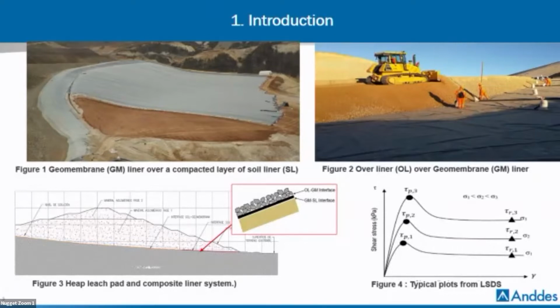You can see in this picture, following the ASTM, the typical behavior of shear strength versus displacement. The shear stress generally increases until the peak shear stress. It should be noted that beyond the maximum displacement of the test, there is no additional reduction of the shear strength, indicating that in this specific case, as in many others observed in testing results, especially in large-scale shear tests for mining applications, the post-peak shear strength is very similar to the peak shear strength.